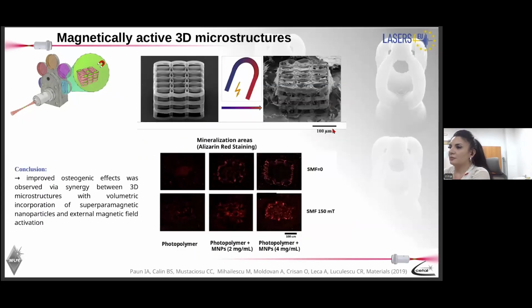And the in vitro test, I will just show you briefly. We have used here a dye, alizarin red staining, which shows zones of mineralization within the tissue in the shape of calcium phosphate, like in natural bone, and the best result was here. So when we have a structure with 4 milligrams per milliliter magnetic nanoparticles inside and exposed to static magnetic field.